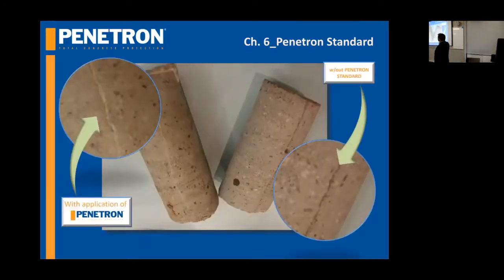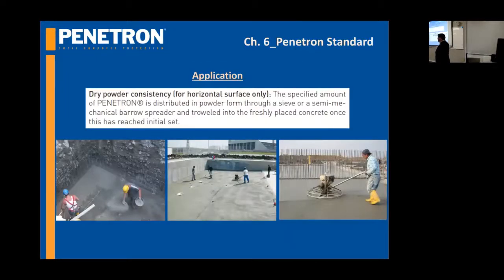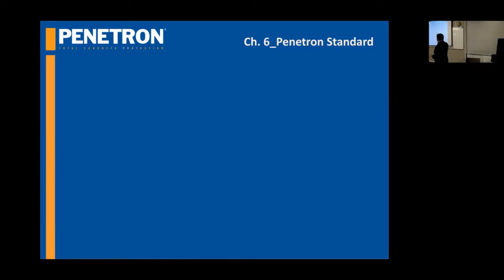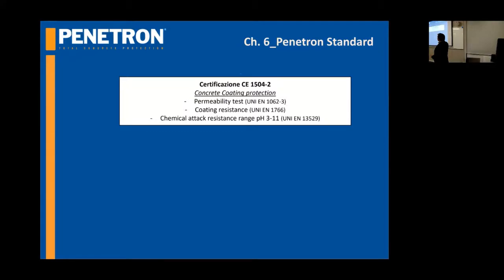This is a typical application. You can see how the crack is sealed and how it's not when it's not applied. There is another application for Penetron Standard for new concrete, only for horizontal surfaces, and it gives a sort of coating to protect concrete, for example against chemical aggressivity, chemical attack. But I will show you better. There are a lot of certifications concerned with concrete coating protection, with the permeability test, the coating resistance and the chemical attack resistance in a range of pH from 3 to 11.